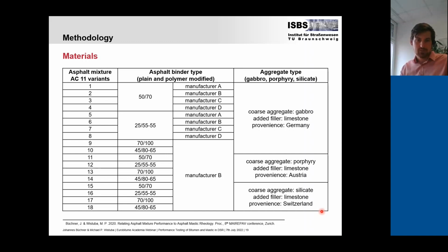For each of the mixtures, we prepared the mixtures, we performed mixture tests, but we also looked at the mastic. So we created for each of the variants the corresponding mastics corresponding to the mix design. So we took the fillers from the gabbro and from the limestone and added this with the 50/70. We also took the fillers here from the porphyr and from the limestone from Austria. So basically, we made an image of the asphalt mixture and created similar and identical asphalt mastic corresponding to each of the 18 variants here.